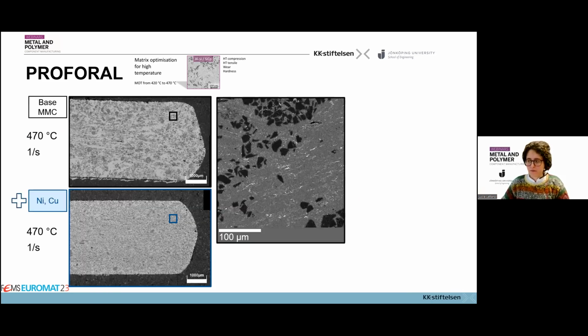We went to look into the microstructures to confirm what was happening. So these are the samples that went under compression testing. On the top, you have the base metal matrix composite. The sample was originally a cylinder that got crushed between the plates at high temperature. This is the maximum temperature, 470. And you clearly see the flow of the material.